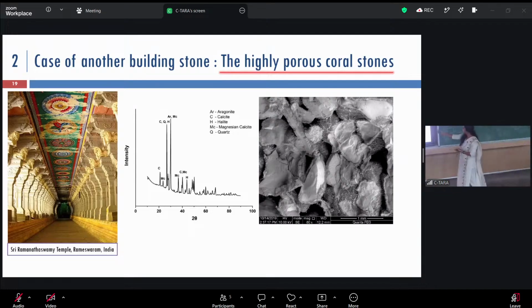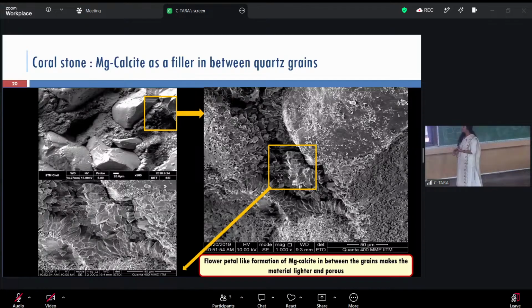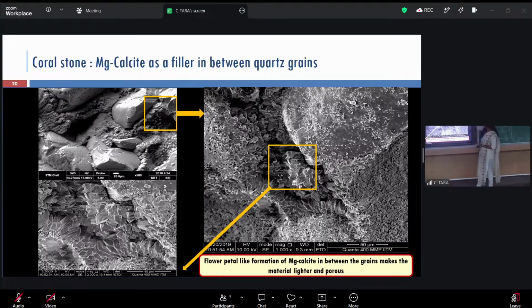This is the microstructural view of the sample, and one part of the structure was damaging. So the authorities wanted to know whether it's because of salt weathering. When we looked through a scanning electron microscope, we saw that this is the structure of it, and these are quartz crystals which are surrounded by a flowery lining like this, which is very, very porous, which was magnesian calcite, Mg plus calcite. And this is very light, very porous and fluffy. And because of this, actually the stone is very porous or floating. That's why it's called floating stone.